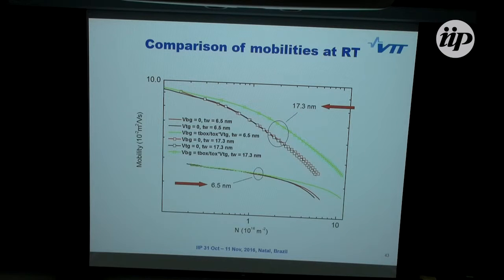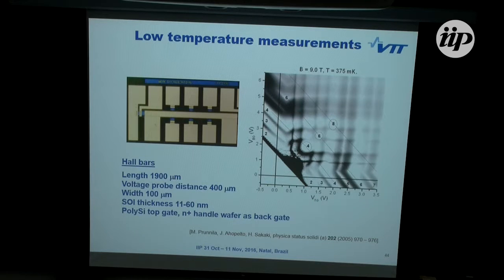These are the data plotted in a more traditional manner: density of carriers and mobility, for 17 nanometer thick. These are when the carriers are on the top or bottom edge of the channel, and this is in the middle with the volume inversion effect. And this is a 6 nanometer thick membrane, the same thing. The mobility is half, but it's not completely a disaster, even for these 6 nanometer thick membranes. So we can say here that the electrical properties are not affected too strongly by the thickness, but the thermal properties are. I'm not going to go into these things, but when one goes down to low temperatures, one can see quite nice things in the Shubnikov-de Haas measurements and so forth.